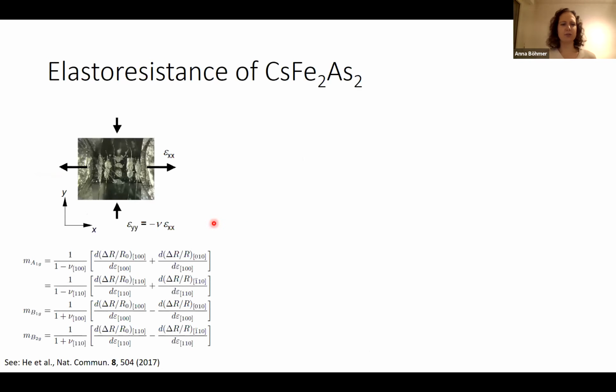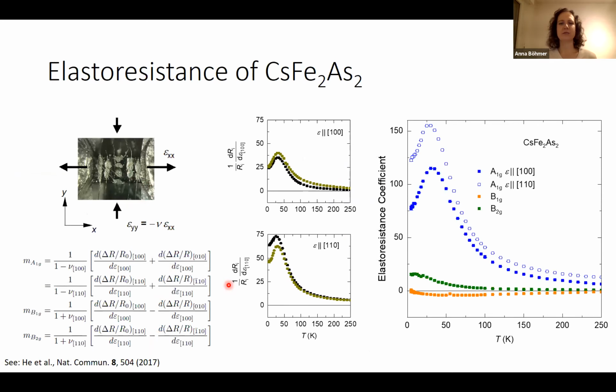And here we use an 8-contact configuration to get longitudinal and transverse resistance at the same time, inspired by this work here. And again, the same symmetry decomposition for the coefficients. And here's already a result for the cesium sample. So the longitudinal and transverse elastoresistance for a sample in 100 direction and in 110 direction. And you see differences to our previous systems. There are no more sign changes here. This means that the A1g elastoresistance is dominant. It's huge here in blue. And the B1g and B2g components are rather small, much, much less than the A1g.